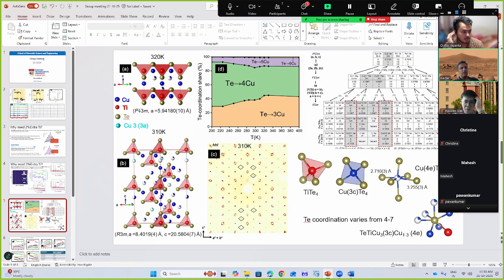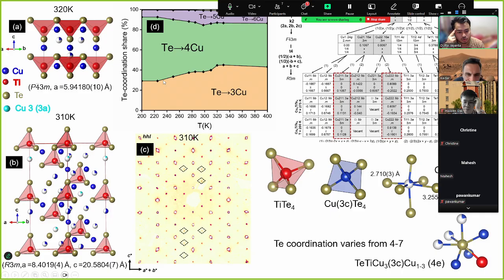So some theoretical explanation should be sufficient. You don't need to wait for some fantastic theory. Just some theoretical support to show that should be good enough. Yes. And actually, Andy calculated the local telluride coordination, like how much it is bonded with copper. At increasing temperature, the telluride bonded with 4 copper decreases, and bonding with 3 copper and 5 and 6 copper increases.